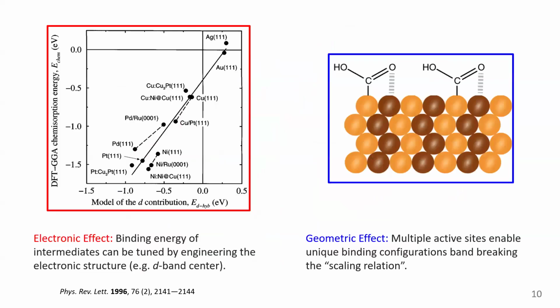Specifically, why that's a useful strategy is that by having alloyed, multi-metallic systems, we can begin to affect the electronic structure of the material, and by tuning the electronic structure, we can tune the binding energy of intermediates, which affects the catalyst activity through the Sabatier principle. That's known as the electronic effect. On the other hand, having multi-metallic systems creates multiple active sites in the vicinity of the adsorbate, and that also contributes what's known as the geometric effect, where we can have multiple unique binding sites, so that we're not limited to a single binding energy.